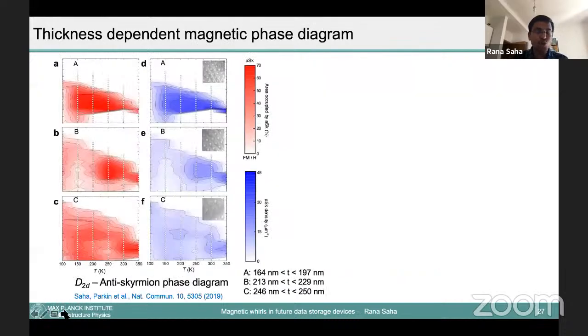I will go a little fast, I am losing time. So they have a wide range of temperature and field stability. These are the phase diagrams. You need to know at what thickness you can stabilize this anti-skyrmion, because when you make a device, you need to thin down or change the thickness. So you need to tune to the right thickness where you can have these magnetic anti-skyrmions.